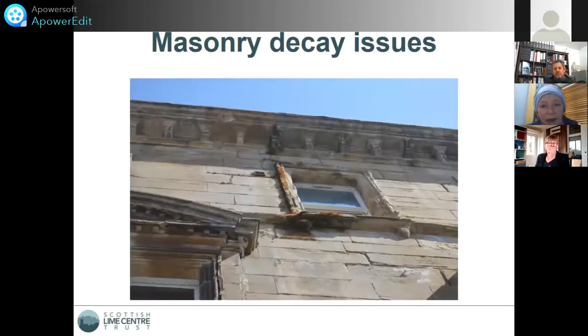I don't know if you can see, but the overhanging cornice on this shot has open perpendicular joints, and the whole point of these overhanging cornices is to provide shelter to the masonry walling beneath. And clearly, if you've got open perpendicular joints, that's going to allow water access to cascade down the face of the wall. And these can be particularly difficult to fully fill because it's difficult for a mason to get a pointing key in to the depth of that wall. And we've actually developed quite a clever grouting system where we use a liquid lime mortar encapsulated by a modeling clay temporary joint filler, and then we can pour the lime grout into the open joint so it's fully filled.